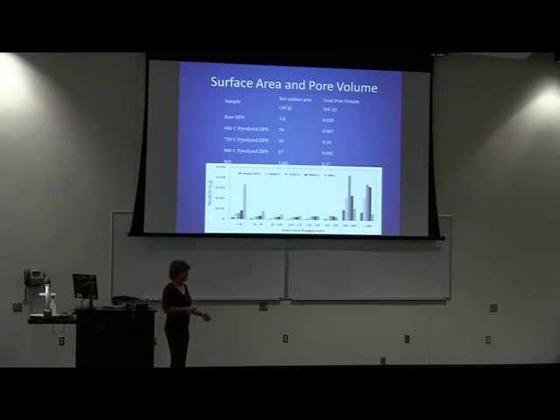And then there's a commercial carbon that you'd probably find in your Brita filters. But it's from Calgon Carbon, and it's about 1,100 meters squared per gram. So it's really, really porous. But when you look at the pore size distribution, this light colored here is the BPL. Almost all of the BPL's pores are less than 6 nanometers, whereas for the DPS, most of them are between 20 and 80 nanometers.